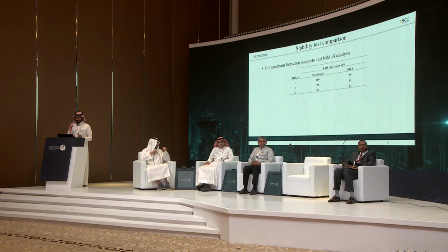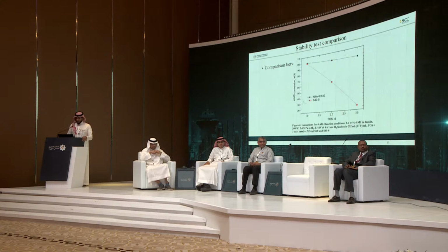For the catalyst stability, we want to compare the NiMoS catalyst over the support and the support itself. What happened is that during the 3 days time on stream, the NiMoS catalyst over the S40 is more or less constant in conversion, and then for the S40, which is the support-only catalyst, we see a decline happening. And why is that decline happening here? It is because we don't have more active sites to hydrogenate the 4-methylstyrene.